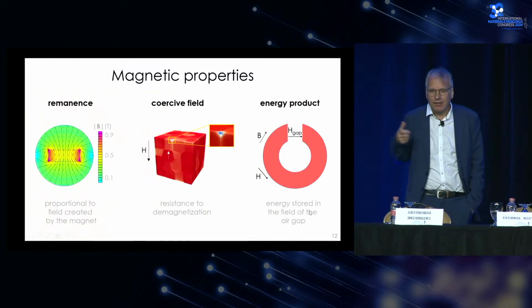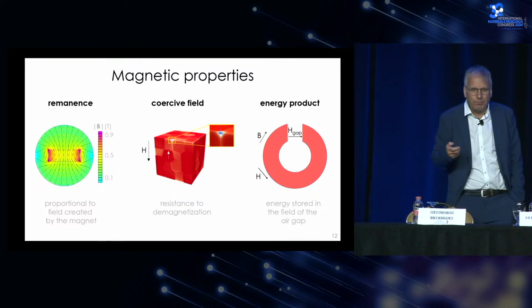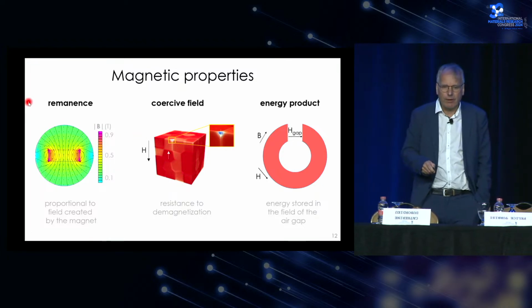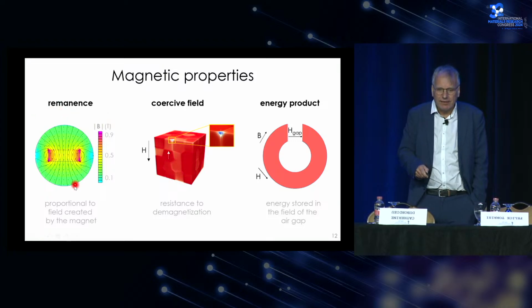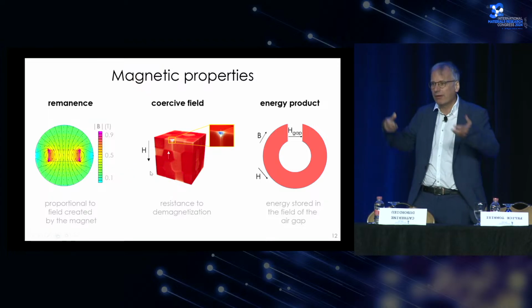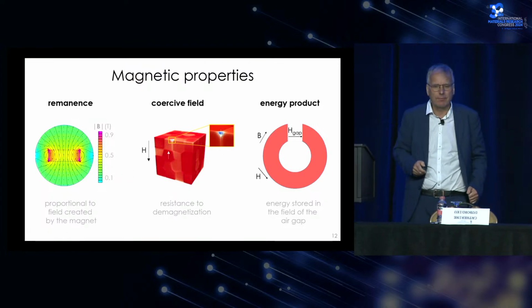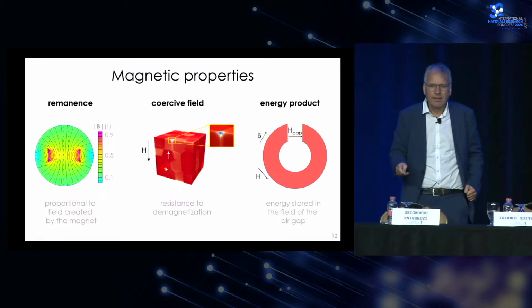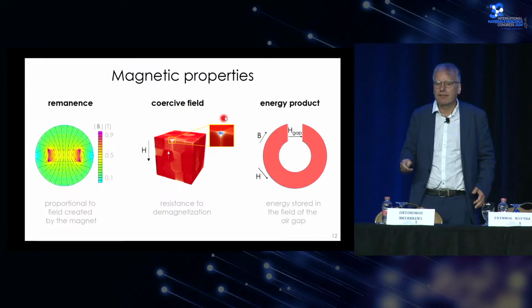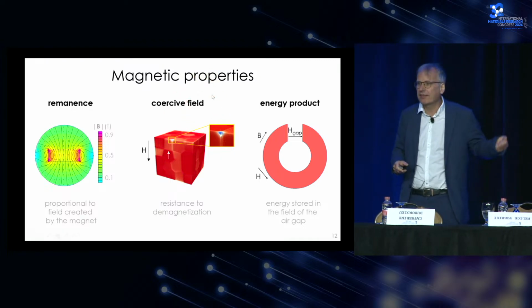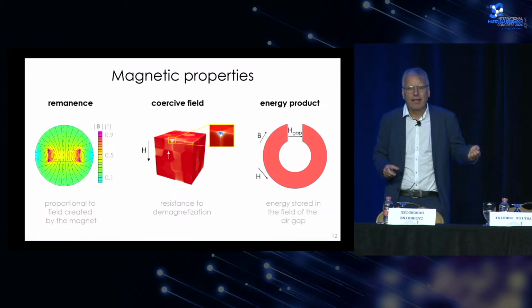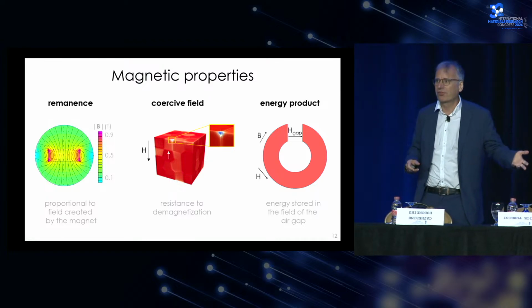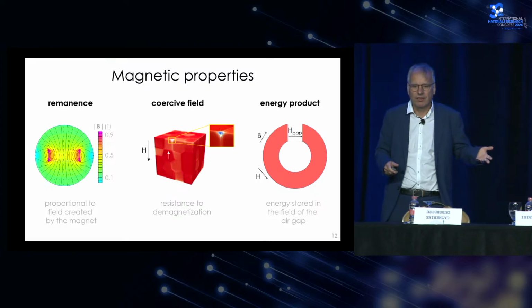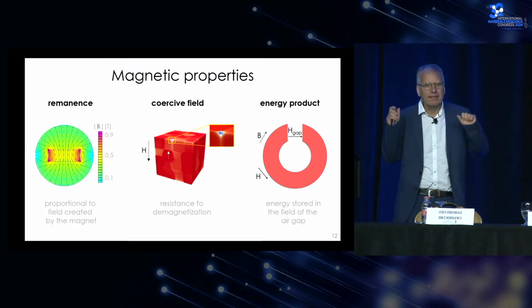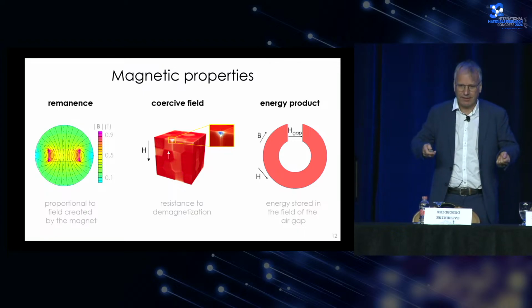So let's have a look at the three properties again. We have the remanence, and the remanence is proportional to the field created by the magnet. So very important, high remanence gives us a high field that the magnet can create. Then we have the coercive field. The coercive field is the resistance to demagnetization. A magnet is always exposed to a magnetic field in application. And what we want to avoid is that the magnet becomes demagnetized.